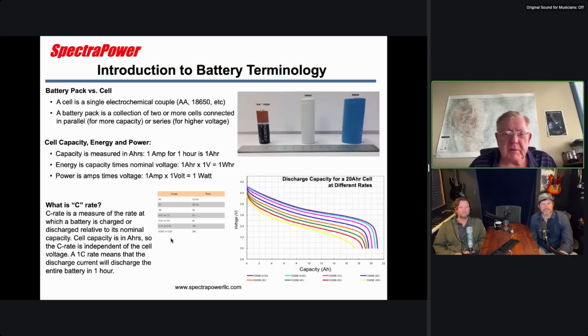And so probably the easiest thing to do is look down here and see 1 C for 1 hour, that's a 1 C rate. So if you discharge the cell, say at 1 amp for 1 hour, that's 1 C. Now, if you up the rate of discharge to, say, 2 amps, then that becomes a 2 C rate, and it's good for 30 minutes. So it's just how quickly you're discharging the energy in the cell. And this has a big impact, especially in electric vehicles. And you can see here in these curves, these are at different rates.